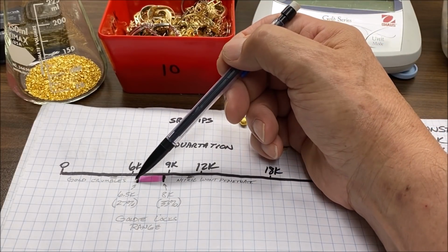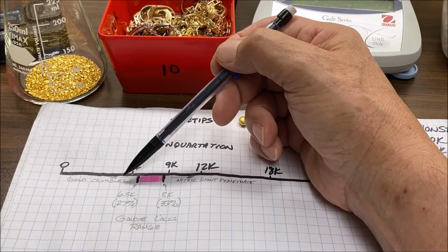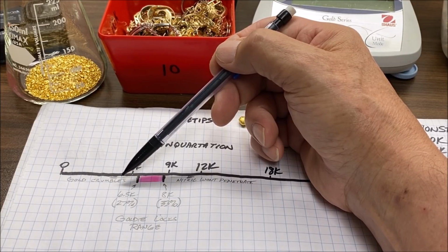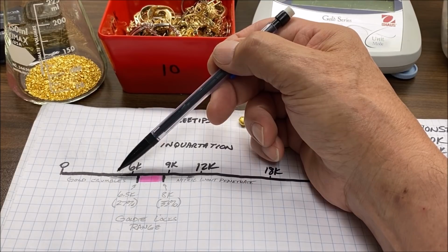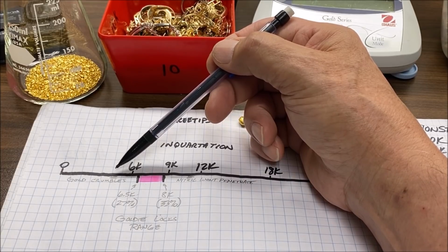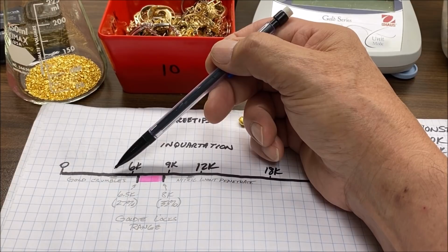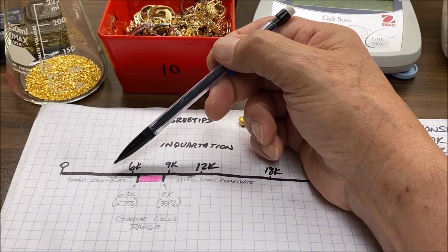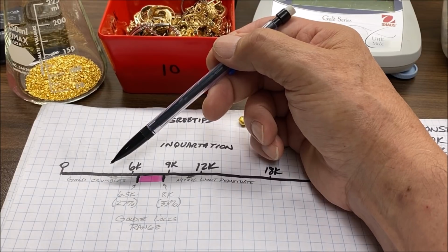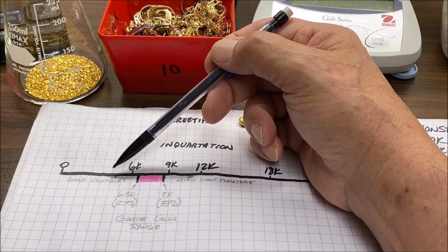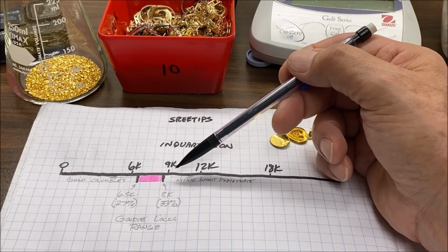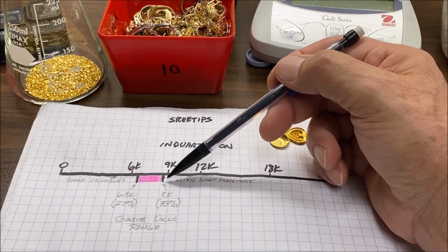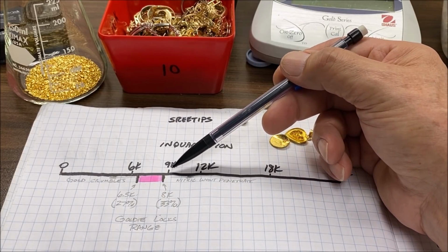If we get below this range down into this area, then we run the risk of the gold crumbling as we do the nitric acid boils, and it'll form a fine powder of gold, or even worse, colloidal gold, that passes right through a filter paper. It makes it difficult to separate the silver-bearing solution from the nitric acid treatments from the gold that's left in our container.